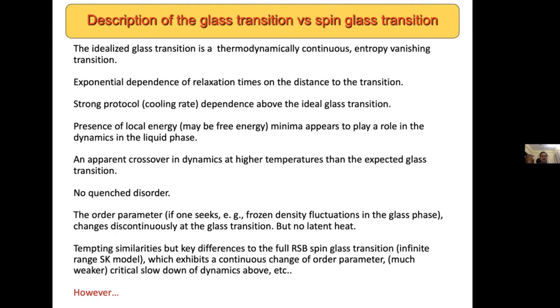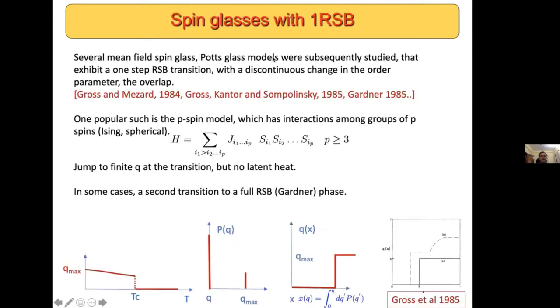However, something that happened again during the 80s is the investigation of several mean field spin glass and Potts glass models that exhibit a significantly different and simpler spin glass transition, which, instead of being a full replica symmetry breaking transition, is what's called a one-step replica symmetry breaking transition, where the order parameter, which is the overlap that was discussed earlier, changes discontinuously.